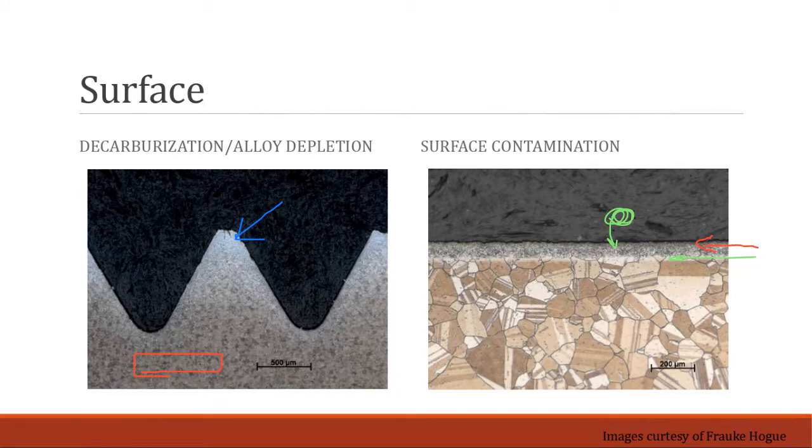And it's really hard to identify in metallography what exactly that surface is composed of. So chemically, it has changed. And since there's a change in chemistry, you have a change in properties. So the real way to go back and identify what this layer is, is to perform EDS mapping, and you can identify if you have an increase in oxygen content, nitrogen content, anything along those lines at that interface.